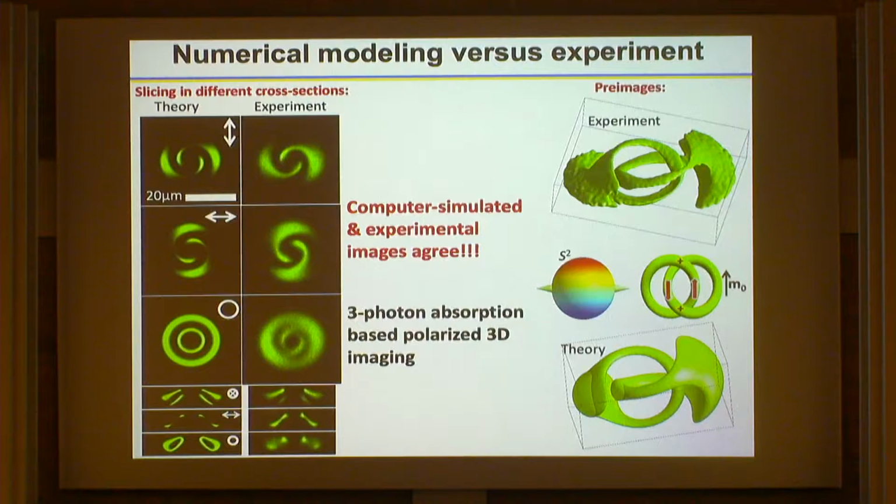How is it dependent on the system size? The pitch of the liquid crystal can be tunable, so you can have different dimensions. In magnetic systems, again, there is an analog of pitch that can also be tunable from sub-10 nanometers to 100 nanometers, and in liquid crystals from 100 nanometers to hundreds of micrometers.